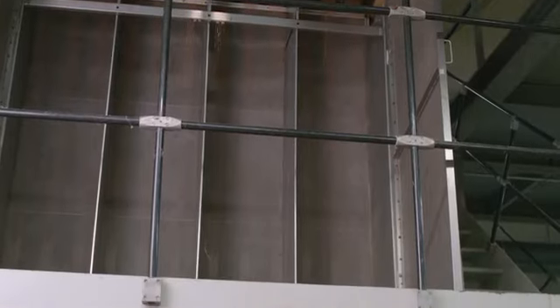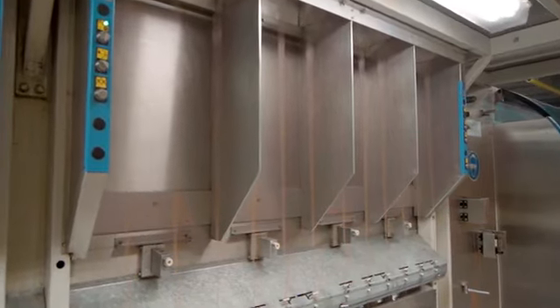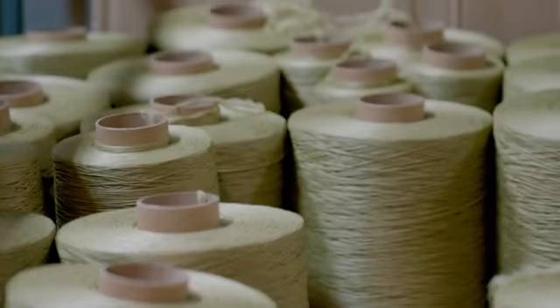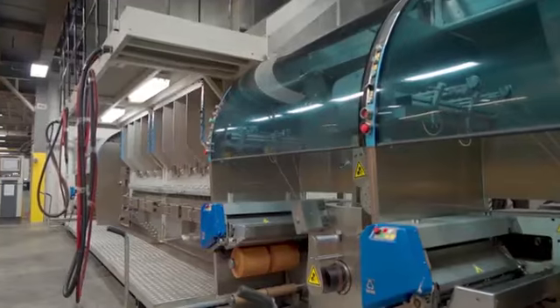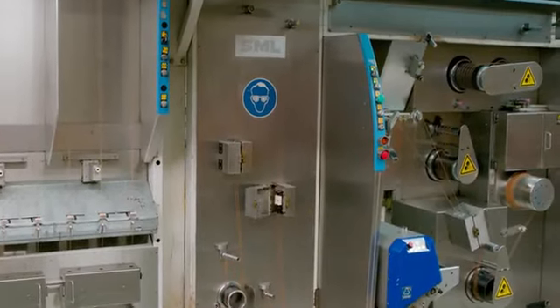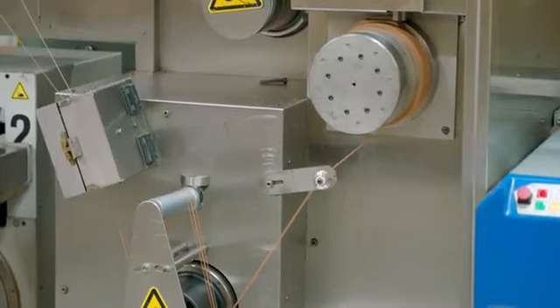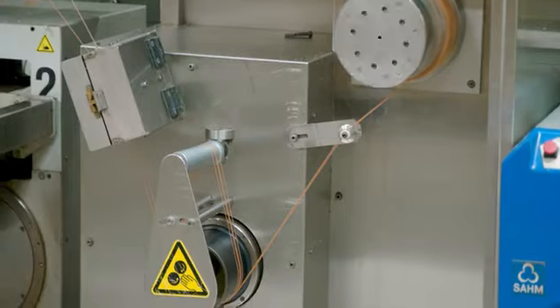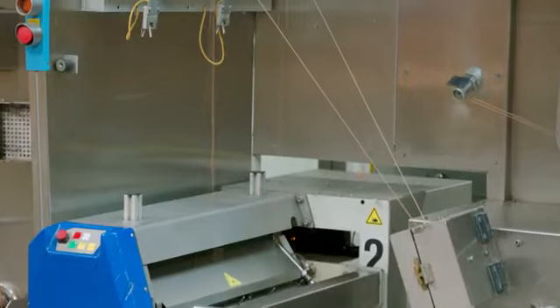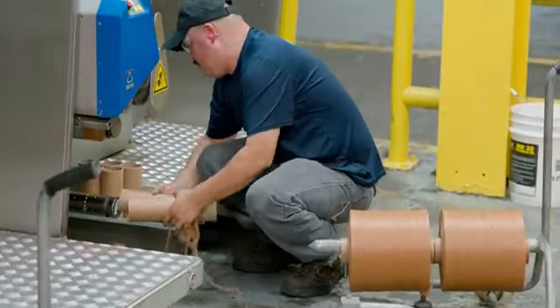Starting from the spinnerets, the filament is air-cooled and a spin finish oil is added for anti-static and friction reduction, which also creates a softer yarn to the touch. The yarn then goes through the stretch and strength phase, through multi-zone heated godet rollers with different speeds, adding bulkiness through the texturizing box, adding tangle to the filaments through the entanglement box, and finally goes to the winder to load the new yarn onto cones.